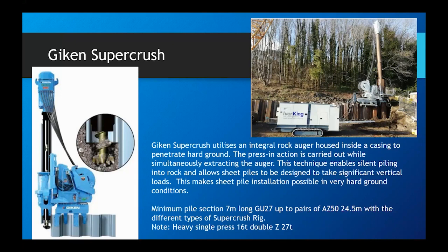Interestingly, I understand that the minimum pile section for this would be a 7-meter long GU27, which is quite a heavy pile for that length. But you can drive piles in pairs, such as Arcelor's heaviest section, the AZ50, up to 24.5 meters with a different type of super crush. But these machines are quite heavy. As I say, the single press weighs 16 tons and the double Z press weighs up to 27 tons. So you do need some serious craneage to be moving this equipment around the site. But in the right ground, in the right conditions, it's a useful tool.